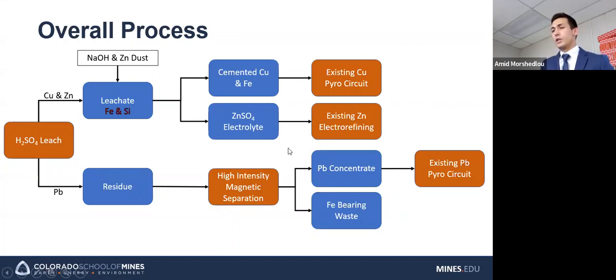So we add some dust to the leachate and we'll cement out the copper and iron. Those cemented solids we can feed into the existing copper pyro circuit, specifically the converting furnace. The iron in the converting furnace is not that big a deal. It'll just oxidize off and go to the slag. And then what we're left after cementation is a solution that is basically a zinc electrolyte. The grade of zinc there is higher than the zinc electrolyte La Oroya uses. So we can mix that in with no problem. And so that just goes to the existing zinc electrowinning circuit.